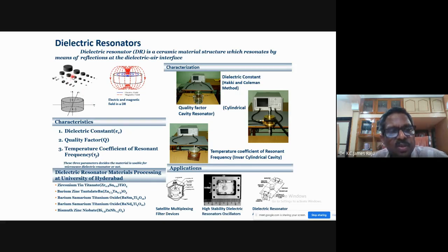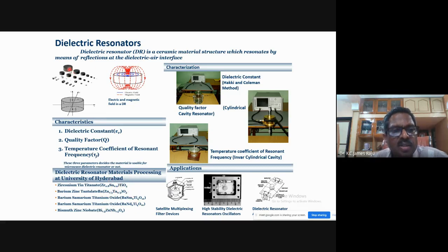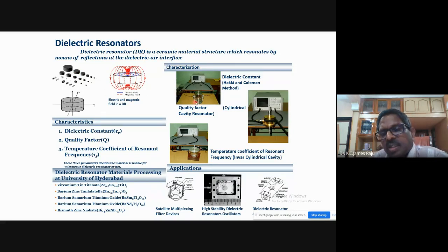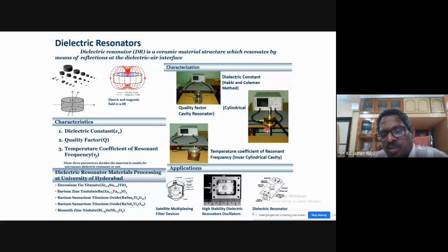For dielectric resonators, we use low-loss dielectrics like zirconia-based and barium-titanate-based ceramics. They are cylindrical pellets; the microwave field, because of the high dielectric constant, is confined within them — the pellet of high dielectric constant and low-loss material itself will resonate. We connect it to a network analyzer using different test structures: one setup identifies the mode and resonant frequency of each mode, another measures the quality factor, and another measures the temperature coefficient of resonant frequency.